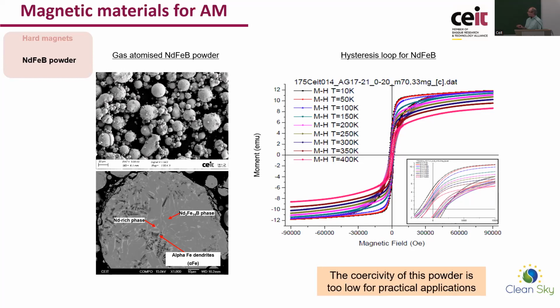The second problem is that the powder is isotropic, but as well the selective laser melting magnets are going to be isotropic. That means that the maximum remanence that we are going to have is about 0.5, 0.6 Tesla, which compared with an anisotropic sintered magnet, which has a remanence of 1.3, 1.4 Tesla, is quite low. If the remanence is very low, you have to make your motor bigger, which was not possible in this case. So finally, we have not made a magnet by additive manufacturing in this project, and the magnets that have been used are anisotropic sintered magnets